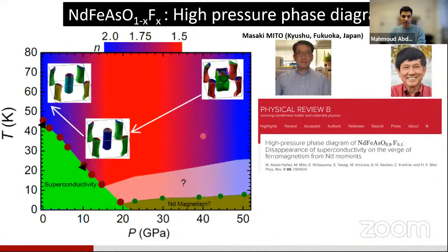Now I have started with doping already. What happens with pressure? We recently published work on neodymium iron arsenic oxygen with pressure. What you can see here, interestingly, is that pressure suppresses superconductivity and induces such a kind of magnetism. So we are still working on this to understand what kind of magnetism we have here, and what the link between superconductivity and magnetism is. There are a lot of open questions to be answered in this field in order to establish some kind of theory behind these high TC superconductors. And as you can see, the work was also in collaboration with Ho-kwang Mao from China and also Masaki Nito